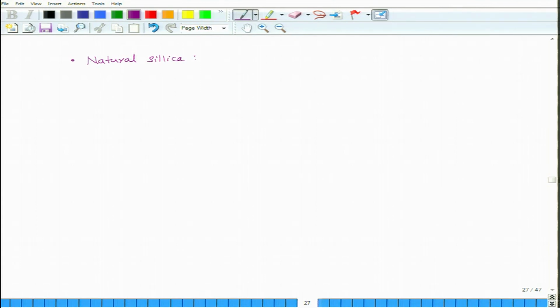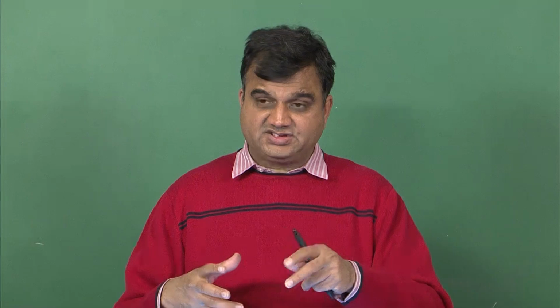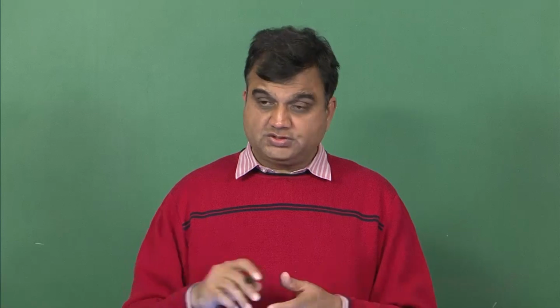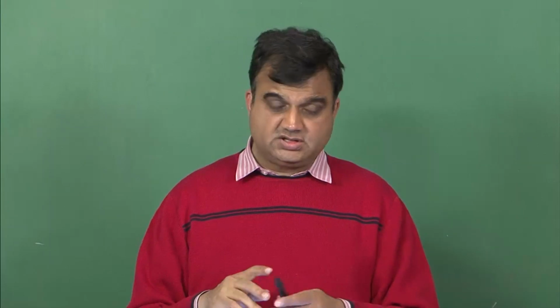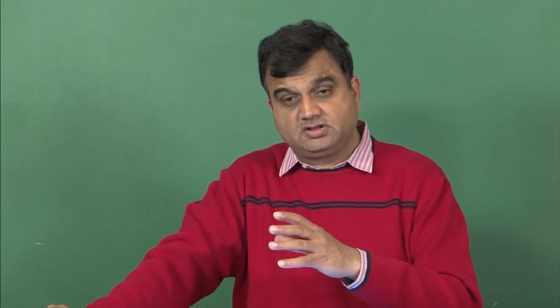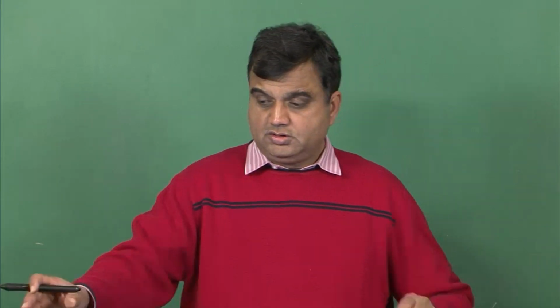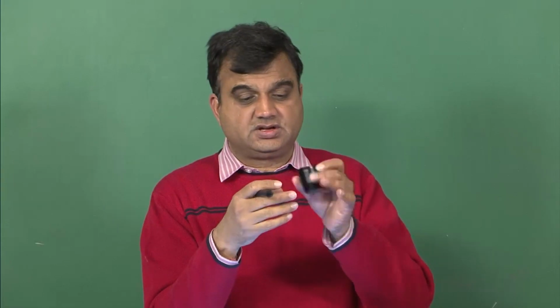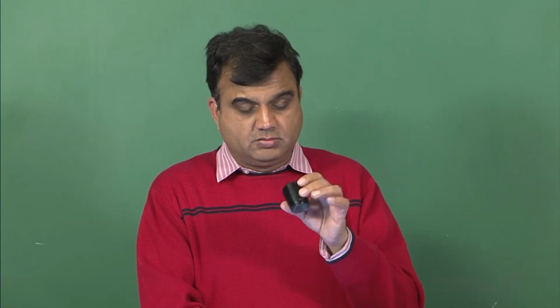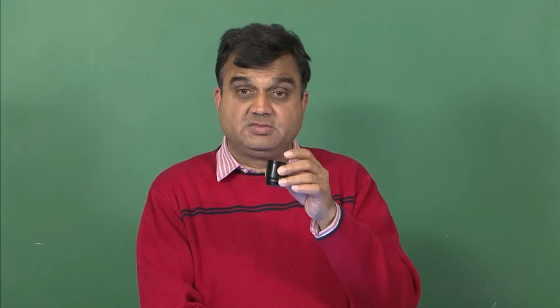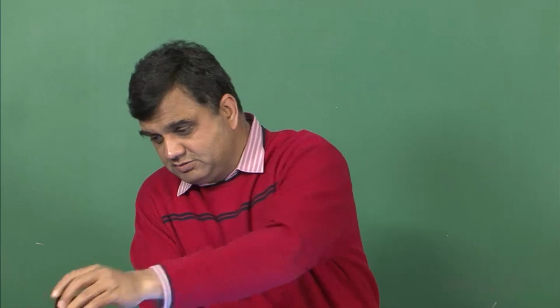Natural silica. Once the material comes out, it contracts, and because you have mixed it with fiber, everything may not contract very uniformly, because you may have short fibers with some specific orientations, and associated with those orientations are specific CTEs. So, it may not shrink uniformly. You think that you will get a part like this, but once it comes out, it may be a little bit deformed part. What you really want is that this type of part should come out. In other words, you want to provide it with some dimensional stability.